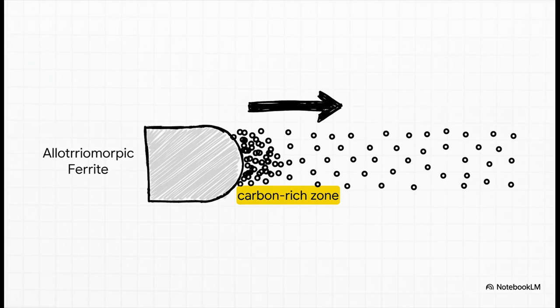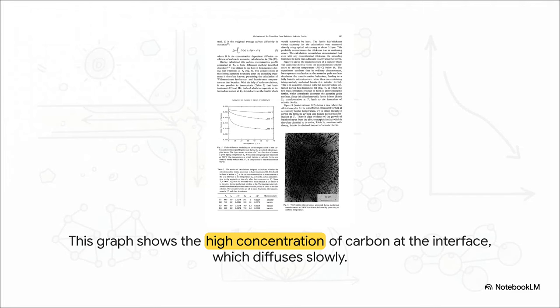Well, ferrite can't hold very much carbon. So as that gatekeeper layer grows, it acts like a snowplow, just pushing all the carbon atoms out of it and into the austenite right next door. This creates a tiny, tiny zone along the grain boundary that is super saturated with carbon. If you look at the data, you can see this huge spike in carbon concentration right at the interface where the gatekeeper formed. And it turns out, Bainite hates high-carbon environments. It simply cannot form under those conditions.